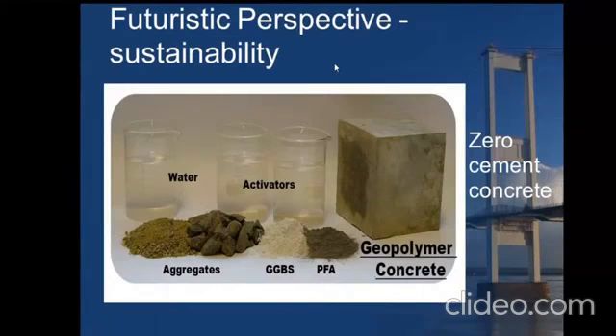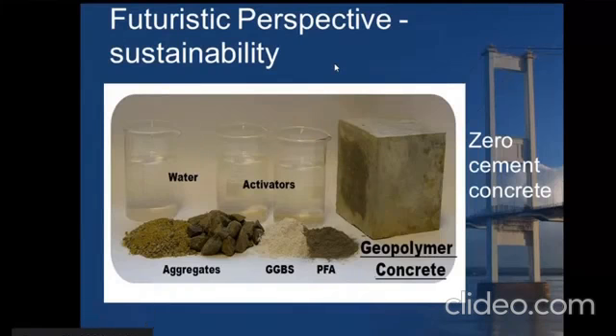So I would like to just give a briefing about this geopolymer concrete. As we know, it is a zero cement concrete. We require a silica rich base. I will not say only fly ash is used. We also use metakaolin. We also use kaolinite, slag, and all these things have been proven to be very efficient raw materials in making a geopolymer concrete, not only fly ash. So I can no longer call it a fly ash geopolymer concrete. There are a lot of silicate rich materials that can be used as a raw material in making this geopolymer concrete, and you can achieve enormous strength in geopolymer concrete.